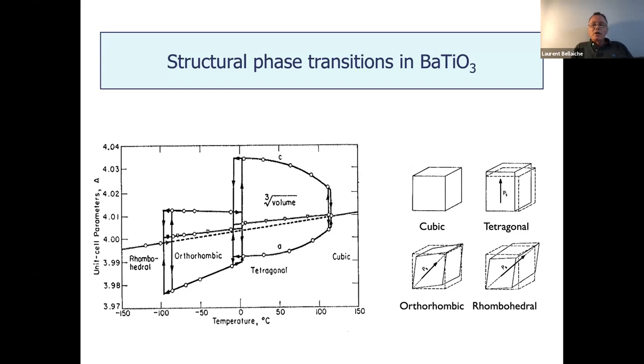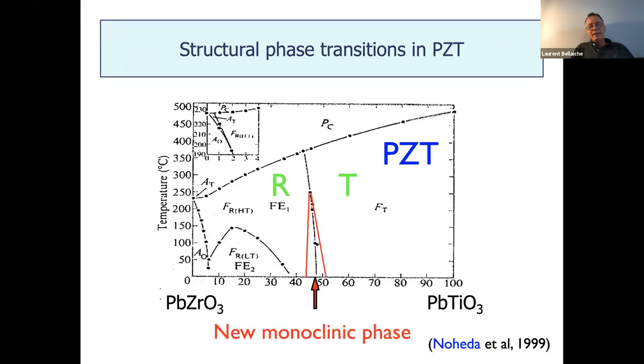In fact, if you look at barium titanate with experimental data, there is a very interesting phase diagram. As you cool the system, you go from cubic, where there is no polarization, then tetragonal, where you have polarization along 0, 0, 1, then orthorhombic, where the polarization is now along 1, 1, 0, and then rhombohedral, where the polarization is along 1, 1, 1. Along these phase transitions, the strain is changing, because the shape of the system is changing along with the direction of the polarization. And if you go to PZT, this is the temperature versus composition diagram.